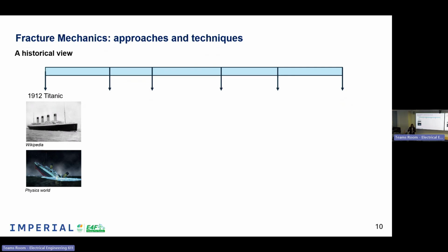It was a dramatic accident because the boat was breaking in the middle of the North Atlantic Sea and about 1,500 people died. After that, an aeronautical engineer was motivated to create the first idea about how cracks can propagate. It was in 1920, and he said that it was completely related to energy. If the energy stored in the solid reaches a certain critical value, which he called the critical energy release rate, then the crack will propagate because it has enough energy to do so. This was a brilliant idea, and in fact it is still being used, because this critical energy release rate is a material property that is now in the day-to-day of materials, but things were still breaking.